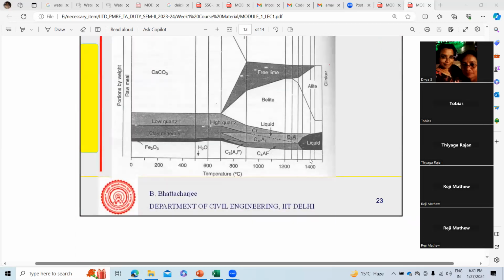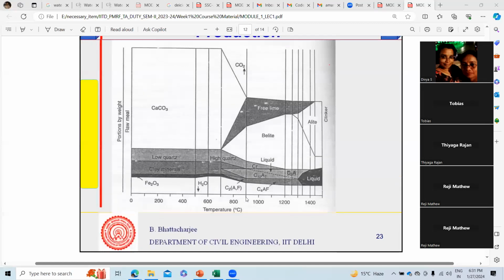So these are the processes I already mentioned, the stages of how it works. In calcination, lime is put in, and with the lime the clay minerals are there. Before it reaches 600 degrees Celsius, the water gets evaporated. Then at 800 degrees Celsius the CO2 is released. Then at 1000 belite is formed, that is C2S, and free lime forms between 1000 and 1200 degrees Celsius. At 1500 degrees Celsius alite is formed.